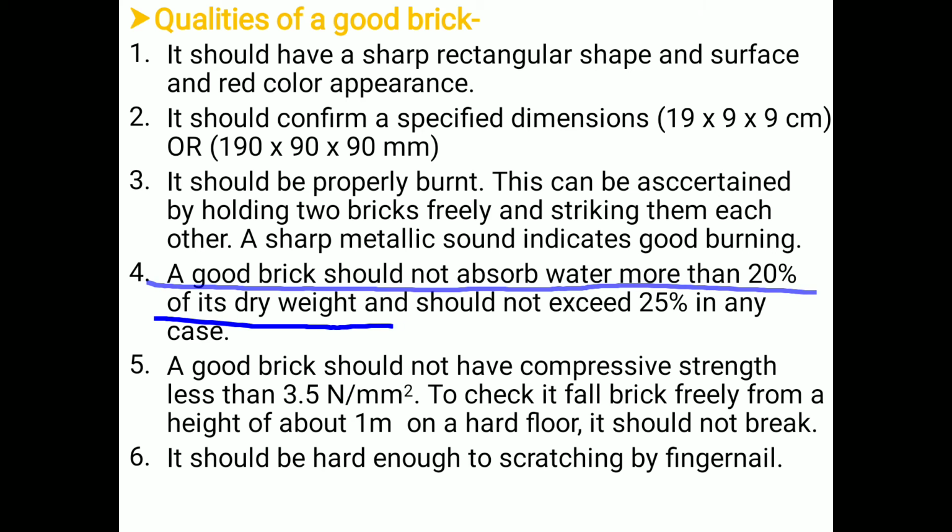The fourth point is that a good brick should not absorb water more than 20% of its dry weight, and should not exceed 25% in any case. So to decide whether the brick is good or not, it should not absorb water more than 20% of its dry weight, and in no case greater than 25%.